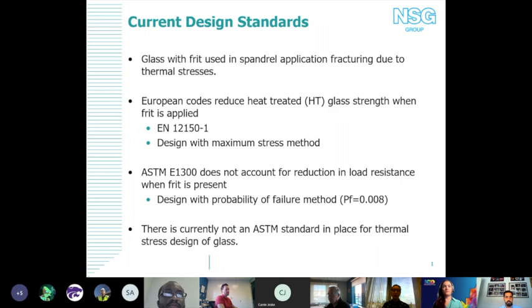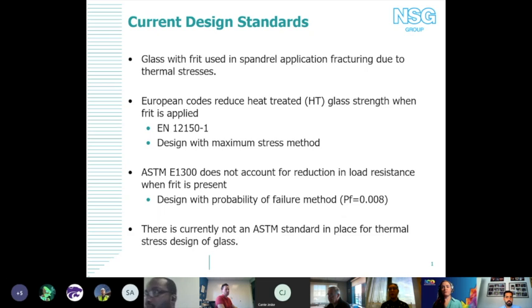Digging a little more into the research, you see that the European codes actually currently reduce the strength of heat treated glass once you go through and apply a frit. And there are some differences between European codes and US codes that make us being able to do this a little more difficult. Essentially, in European codes, they're designing their glass using a maximum stress method. So they assume that the glass always fractures wherever the maximum stress in the glass is. Once you apply frit, they add, I believe, a 30% reduction to the strength of glass.